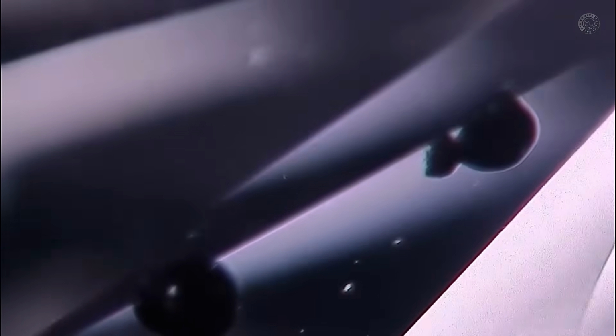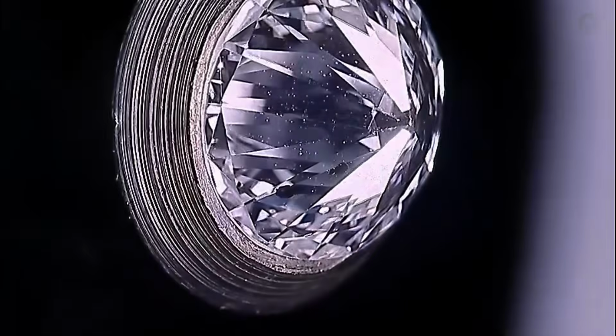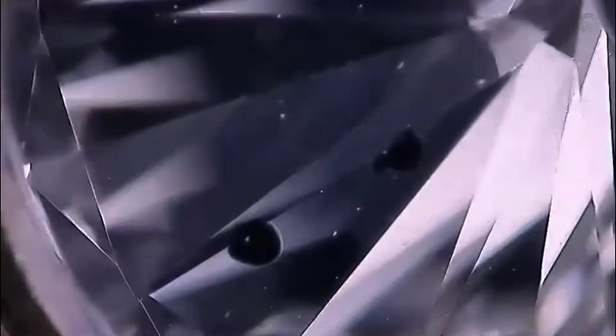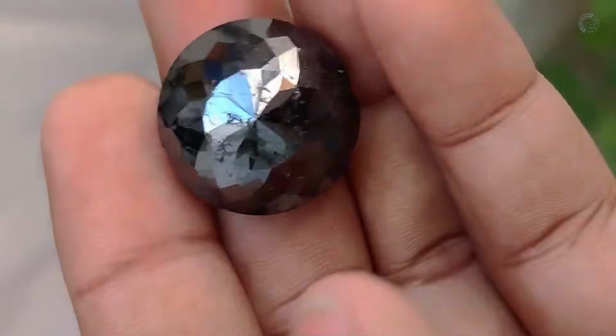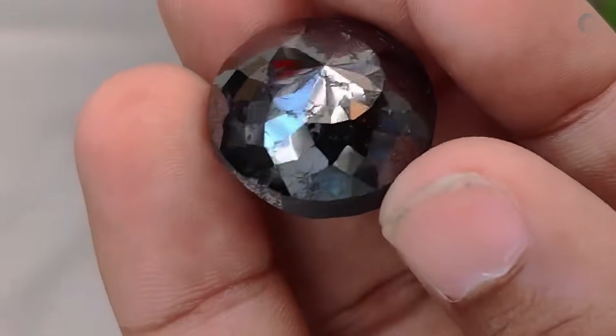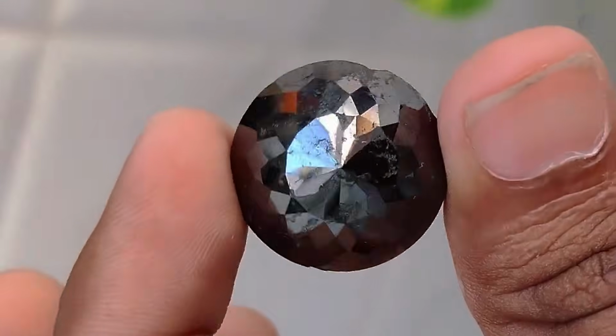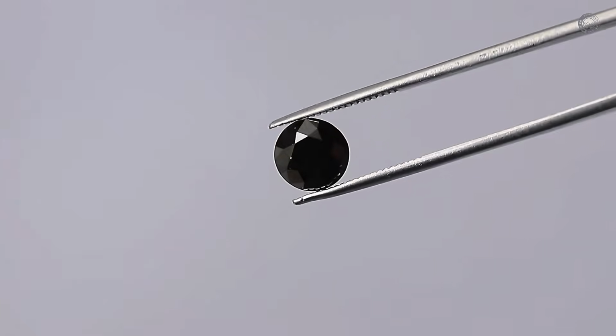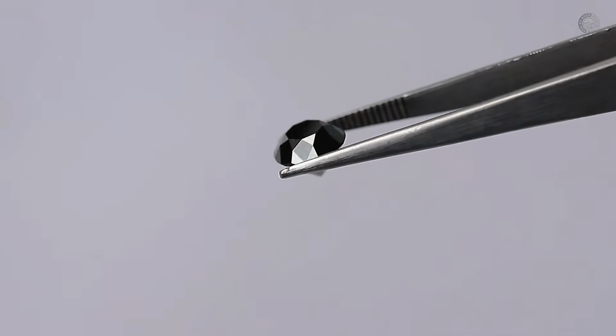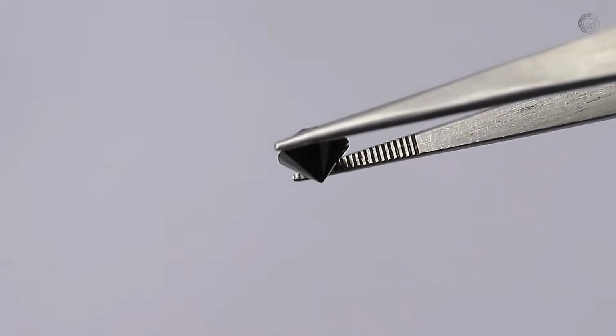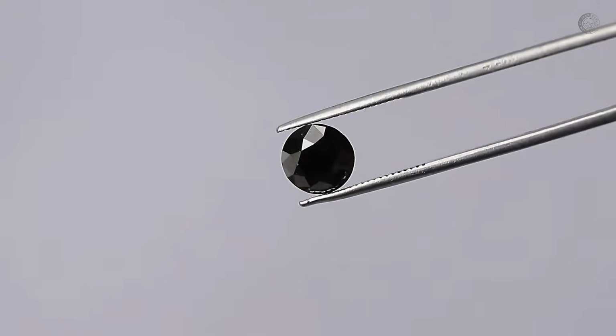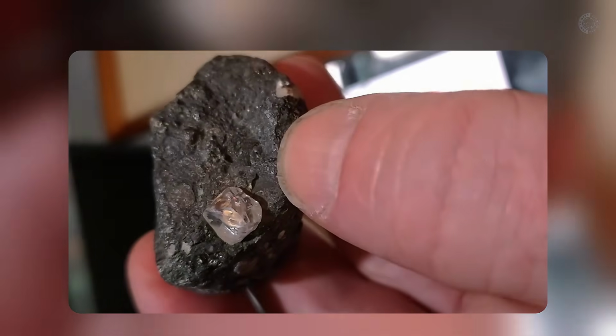The adamantine luster remains strong, edges stay sharp, and under a 10 times loupe, you won't find that internal fog typical of amorphous materials or inclusions broken apart by heat. But it's important to understand the physical limits of this test. Diamond is crystallized carbon. Under extreme conditions, it can change. At temperatures between about 700 and 800 degrees Celsius, in an oxygen-rich environment, diamond begins to undergo surface oxidation. At that stage, the surface may show slight dullness or loss of polish. But notice, this is far beyond what a common lighter or portable torch can reach in a few seconds. In other words, in the context of a home test, diamond will not be damaged.